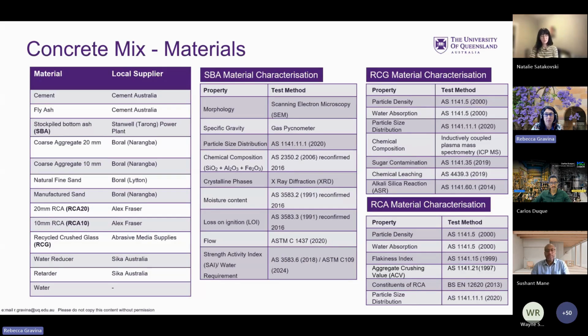For the recycled crushed glass material characterization, it's important, in addition to looking at the chemical composition and the particle size distribution, to also understand the sugar contamination and what the chemical leaching properties are, and what influence the recycled crushed glass has on ASR. That helps you to decide what particle size you'll want to specify when you're dealing with recycled crushed glass in your concrete mixes.